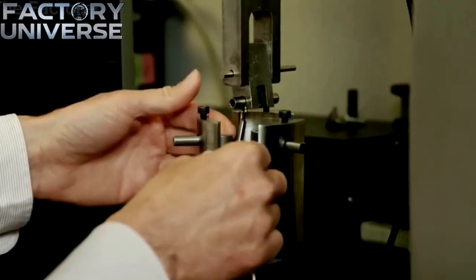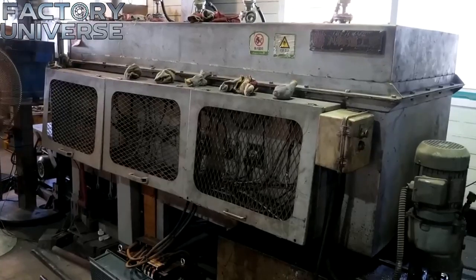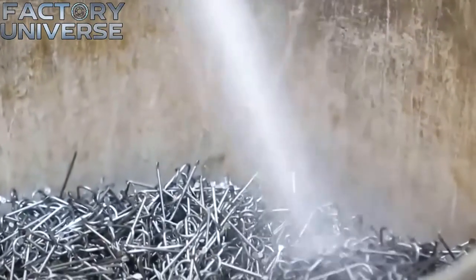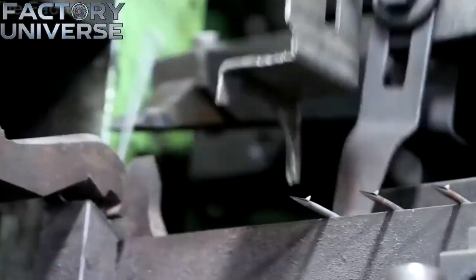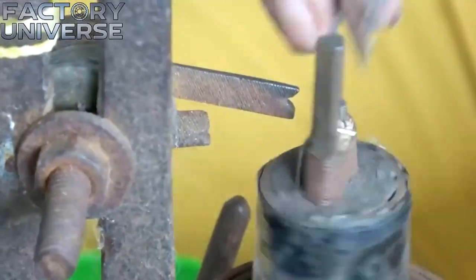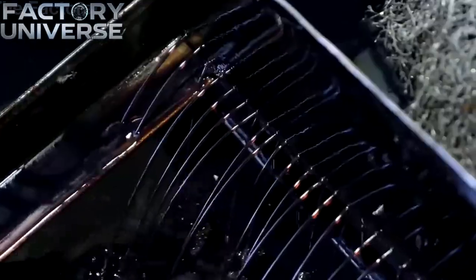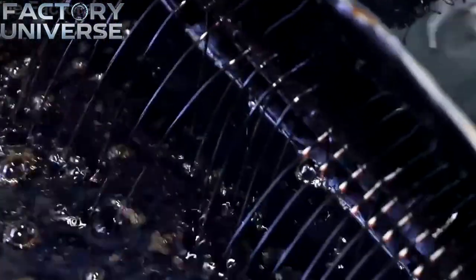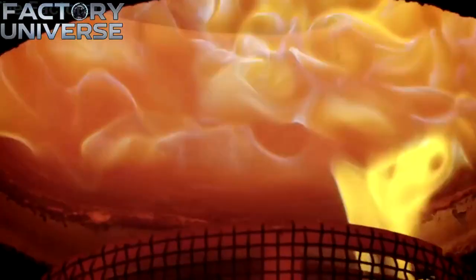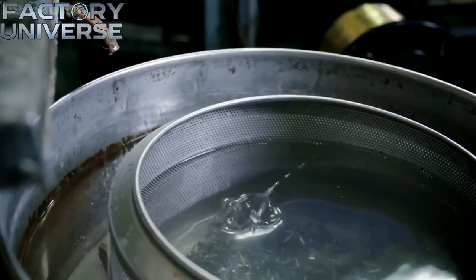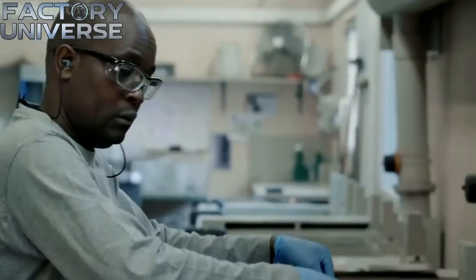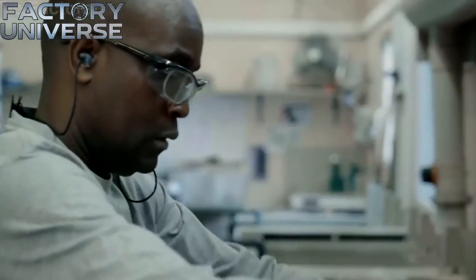1,400 to 1,600 degrees Fahrenheit is the temperature range the continuous hardening furnace reaches as it receives the formed steel. Why is such intense thermal exposure required for a simple metal hook? It would seem that the shape alone determines its function, but without this specific heat, the steel lacks the structural integrity to withstand a strike. This thermal energy causes the internal crystal structure of the metal to reorganize at a microscopic level. But this is just the beginning.